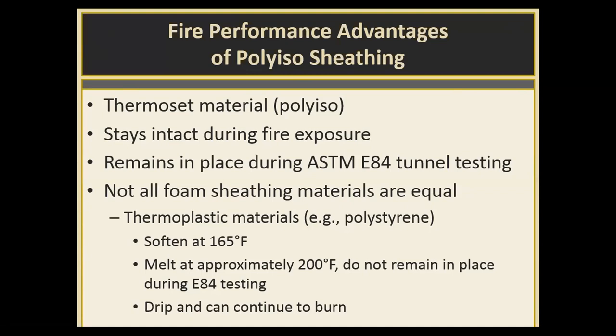Thermoset materials like polyiso are more analogous to the piece of bread, where if you place it near a heat source, it stays in its shape, but it forms a char layer on the surface. It will eventually ignite and burn if the temperature gets hot enough, but the melting point compared to a thermoplastic, thermoplastics soften at 165 degrees Fahrenheit, and they start to melt around 200, whereas thermosets, depending upon the formulation and product, have a combustion point of somewhere between 600 and 800 degrees Fahrenheit, so significantly different. So a thermoset product stays intact during exposure to heat or flame. If you remove the flame, it'll self-extinguish.